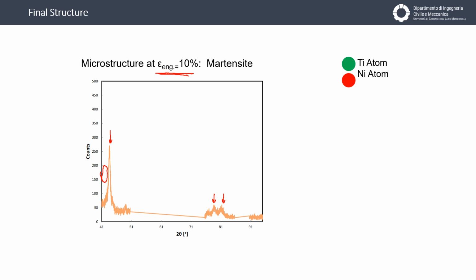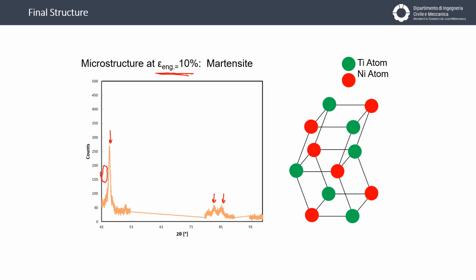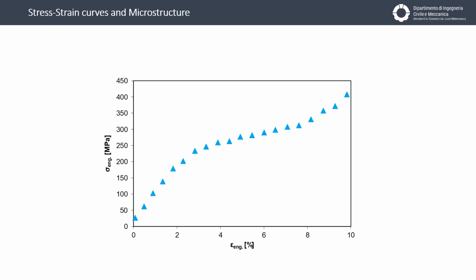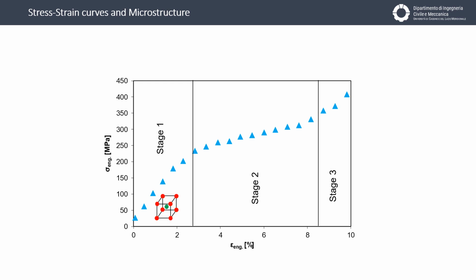Elaborating these peaks, the microstructure seems to be this. It is characterized by an angle different to 90 degrees. This is a monoclinic cell, in which the nickel and titanium atoms are positioned on the vertex of the cell. It means that, for example, in loading condition, we will start using a material characterized by stage 1. Then we have the stage 2, sometimes named as a plateau, but it is not a real plateau, and the third stage. It means that at the first stage we have a presence of a cubic cell. At the third stage we have a monoclinic cell. In the stage 2 we have the presence of both of them, cubic and monoclinic cells.